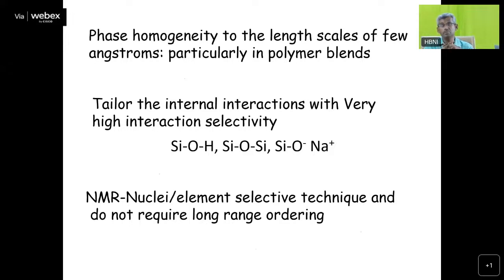That is the most important aspect, because NMR gives the environment around a few angstroms, whereas X-ray diffraction, neutron diffraction or electron diffraction, etc., require long-range ordering to the length scale of a few nanometers, or at least up to 100 angstroms. Only more than that can you get meaningful information. But NMR probes within angstroms, less than 10 angstroms, or even less than 5 angstroms, you can get meaningful information from NMR. That way, one can get information regarding the short range order in a variety of materials.